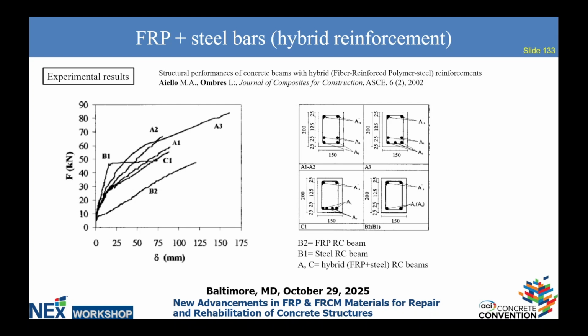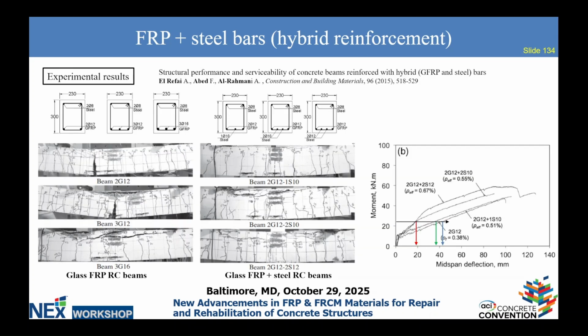But then obviously, there has been other research, and this was part of the database that we've been compiling, where we have pretty much the beams, and you have different reinforcement ratios, different contributions between the GFRP and the steel, but in this particular case, they kept the bars at the same layer. So therefore, you will have one of the two becoming the governing strain, and it will be very difficult to have a balanced curvature where you trigger the failure of all the three materials because they placed the bars in the same layer.